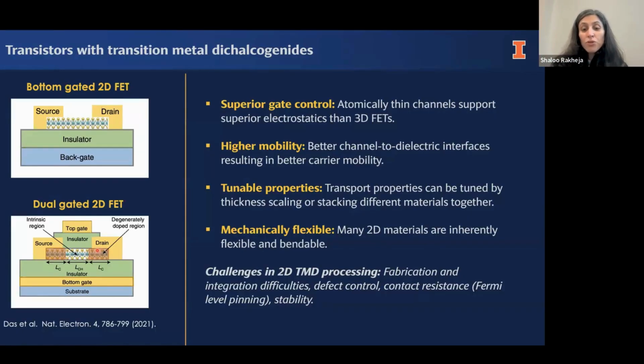So for 2D materials, you can really control how much strain you're applying, and because of their flexibility and bendability, it's very easy for us to apply strain levels up to 30%. Though experimentally, my colleagues have been able to apply up to plus or minus 1% strain in these materials.